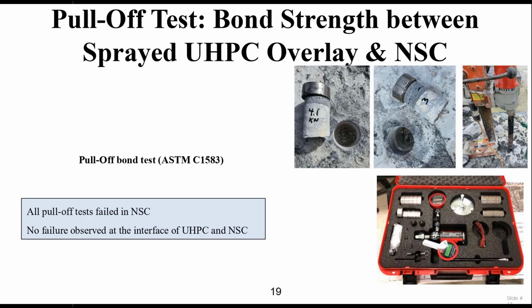I mean, take an example of the steel culvert that I showed you. The overhead we were doing. This concrete, if the mix is right, and if the mix and the equipment is right, you can do overhead. And in fact, in areas like Florida, for example, you have this jet ski that goes underneath the bridge, and then they spray the salt water underneath the bridge, and then you get a corrosion from underneath. And this sprayable UHPC, I think, is a wonderful alternative for those applications.